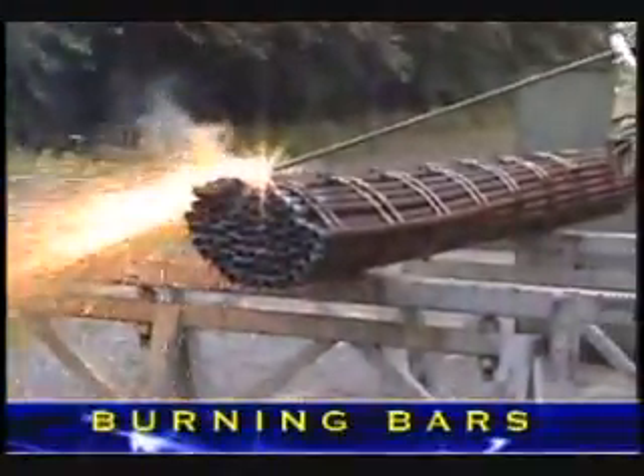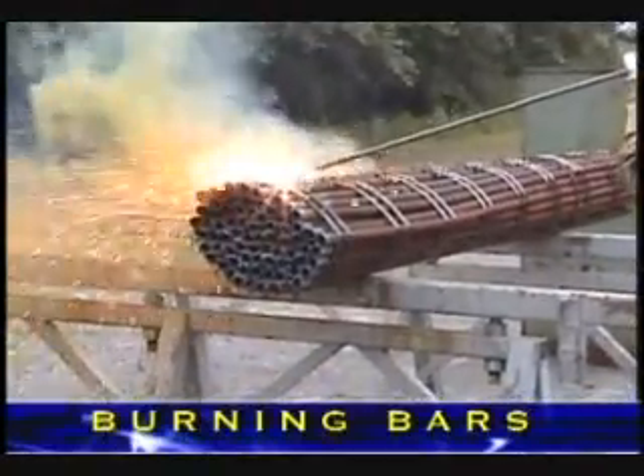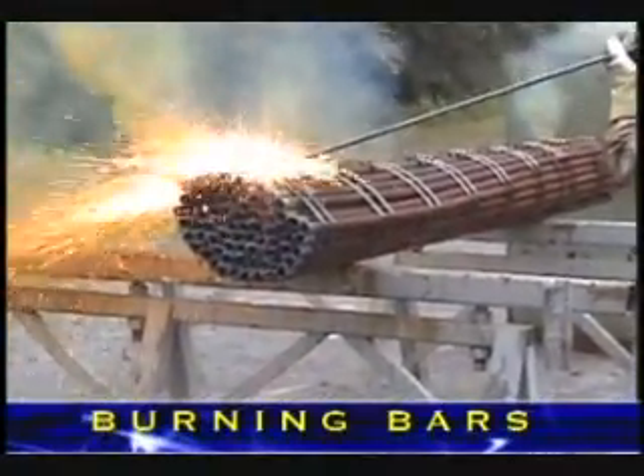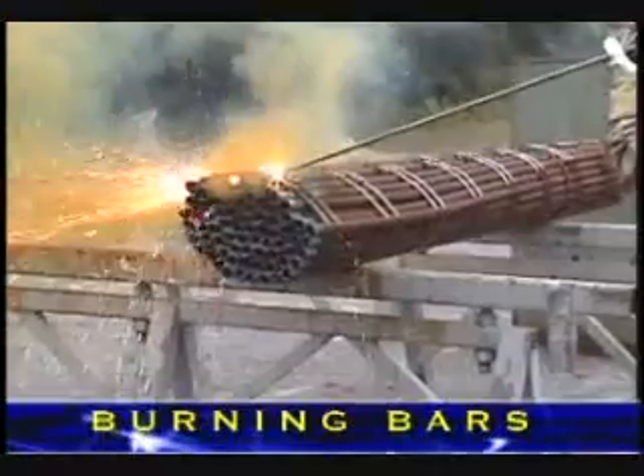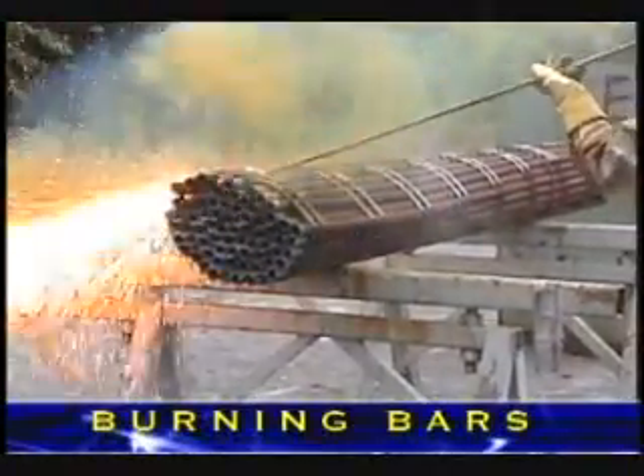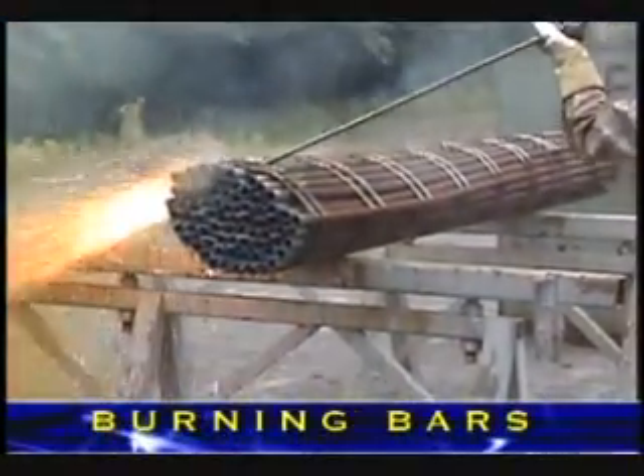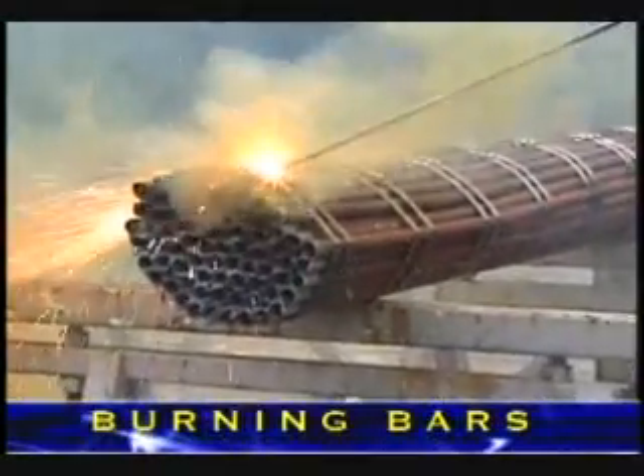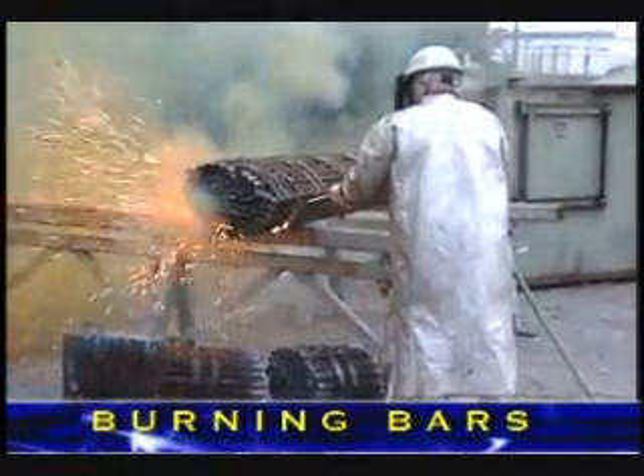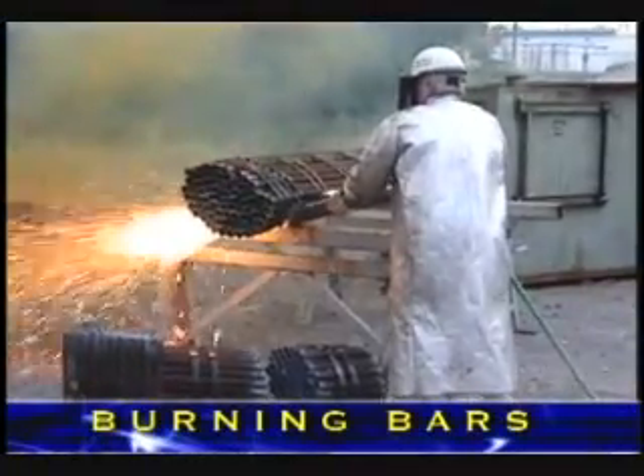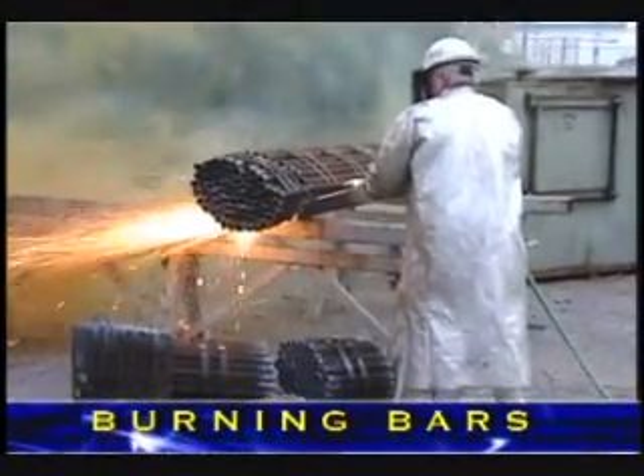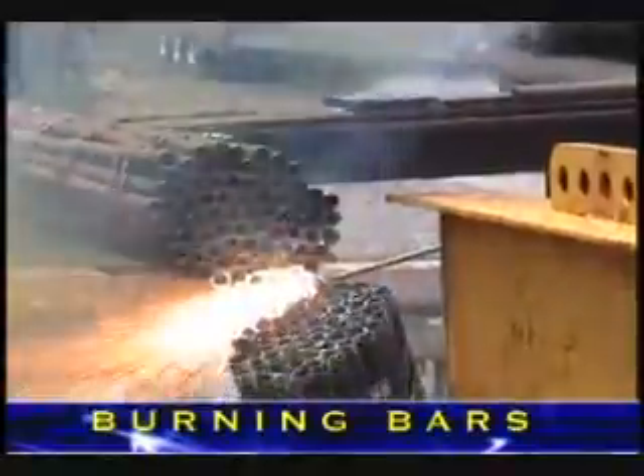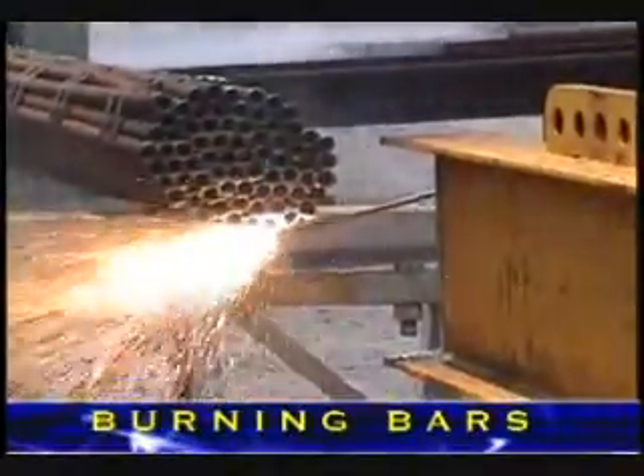Cutting with burning bars is actually easier than with a regular cutting torch. Burning bars work best when the tip of the pipe is in contact with the material being cut. You do not have to maintain a tip clearance. Laminated steel or bundles of steel, such as heat exchangers, can be cut with ease. The operator in this case is cutting a tube bundle that is 18 inches in diameter. The complete cut was accomplished in 3 minutes and required less than one 10-foot 6-inch burning bar.